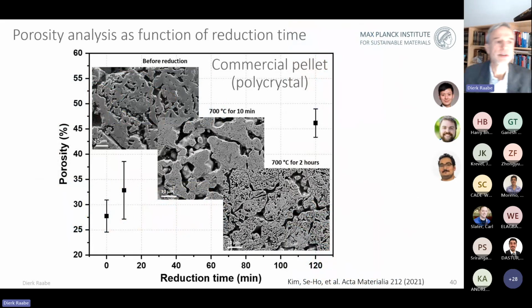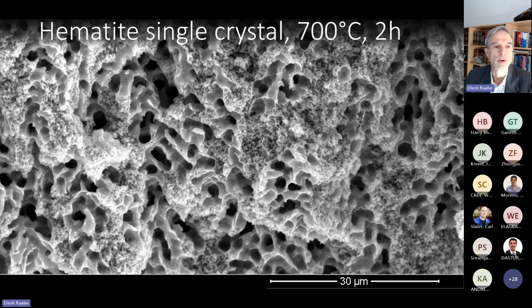Here you can see the increase of the porosity, now back to a commercial pellet, again at 700 degrees centigrade as a function of reduction time. And you can see that the porosity starts from the inherited one from the sintering, like 27%, and ramps up to more than 40% towards the end of the reduction due to the mechanisms that I have explained to you before. Now, when you break these samples and look at the topology and distribution, you see that you have very coarse porosity, and some of these coarse pores being also connected, forming complex channel patterns. And you have also very fine pores, as you can see. So it's like a Swiss cheese, but much, much more complicated. And that is extremely important to understand the mass transport and the water formation in these commercial pellets.